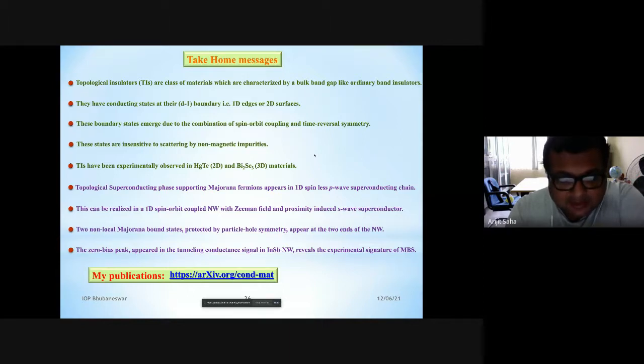And from the experimental point of view, it is the zero bias peak, because they appear at zero energy. The zero bias peak that appears in the tunneling conductance signal reveals the indirect experimental signature of Majorana bound states. Also, I am not saying that what I am showing is a smoking gun signal of Majorana, unless and until you show experimental evidence of non-abelian statistics or some other very concrete signature, it is very hard to say that this is really Majorana. So the debate is going on, the research is going on.